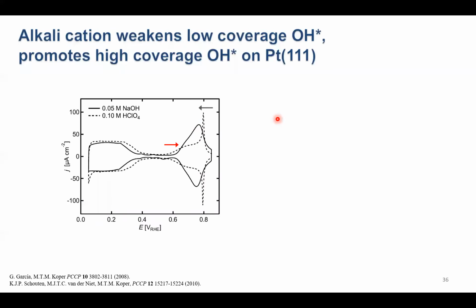I'll just briefly mention that we can use the same understanding we developed on the step sites, the same mechanism, to explain the effects of pH on hydroxide adsorption on platinum-111. It's just that the effects on this flat platinum-111 surface are a little bit more subtle than what we see in terms of the effects of pH on the step sites.